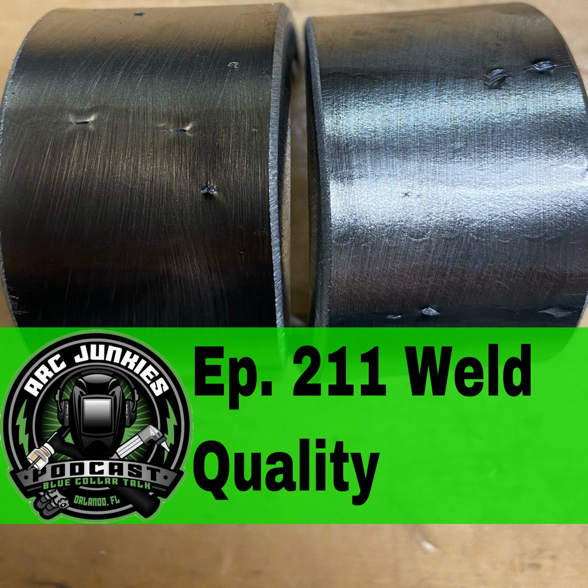So case in point, let's take a fillet weld for an example. Put the fillet weld in a horizontal position, because we only have to deal with a vertical plate and a horizontal plate at that point. Now, let's say we're using shielded metal arc welding. If I point my electrode too far at the horizontal piece, the flat piece, I'm more than likely going to develop some undercut along the vertical plate, at the top toe of that vertical plate. Likewise, if I favor more of that vertical plate, I'm probably going to get some undercut on the bottom toe of the horizontal plate. So improper travel angle is a big cause of undercut.